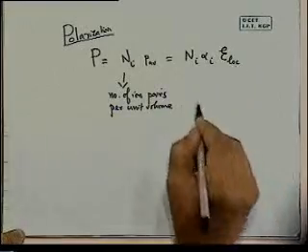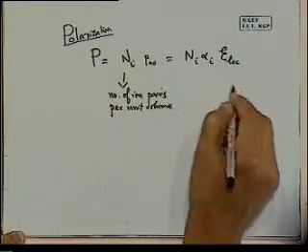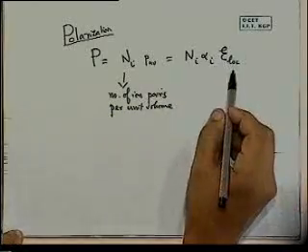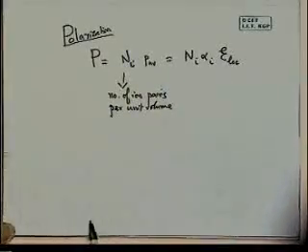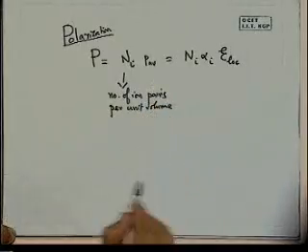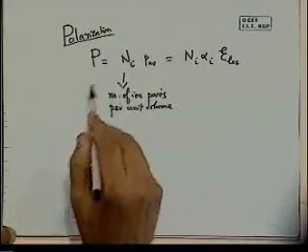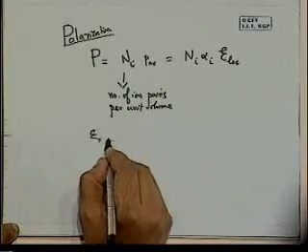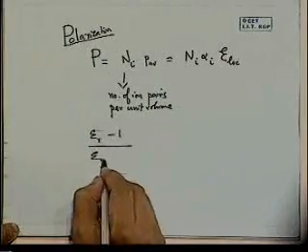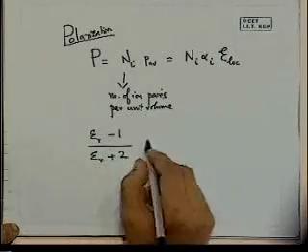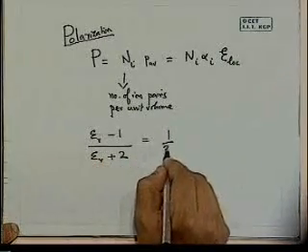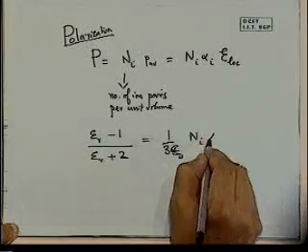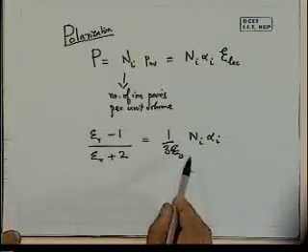If you want to account again for correctness, to use the local field, then either, if you take the approximation, we will use the applied field, or to be more exact, we use the local field. And using again the same kind of approach as before, going through the equations, you will end up here also with a similar expression relating the relative permittivity to the polarizability, except that now we have Ni alpha i.